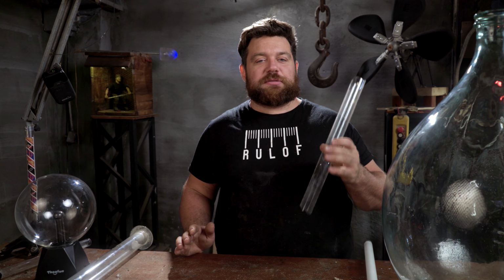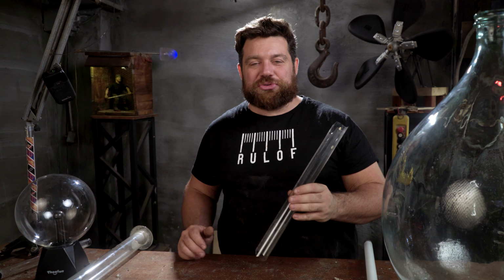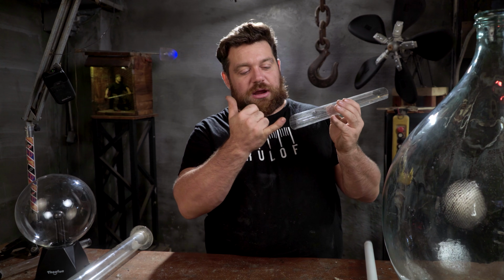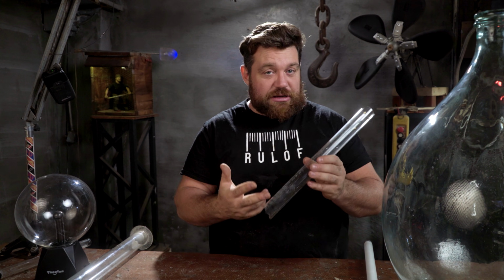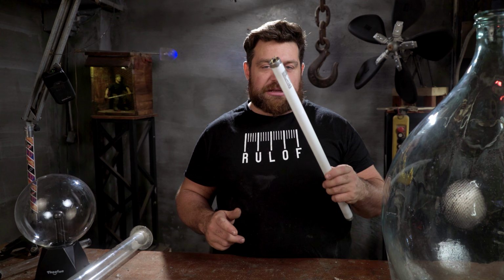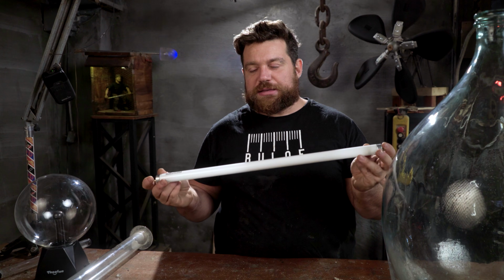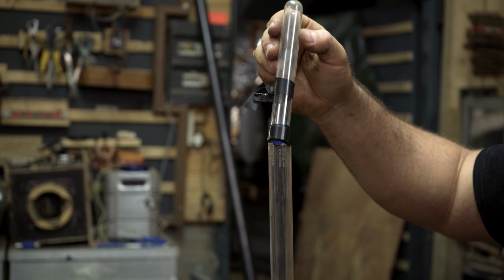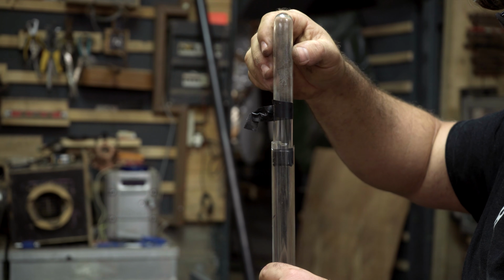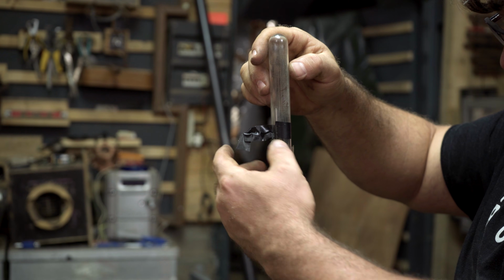This was airtight, but once it starts to cool down, a little crack happened on the side, and this isn't airtight anymore. So this idea doesn't work. I try again with a smaller neon tube. Maybe the glass was a little bit thicker, but I had the same problem. So the solution is just to use no fire at all.